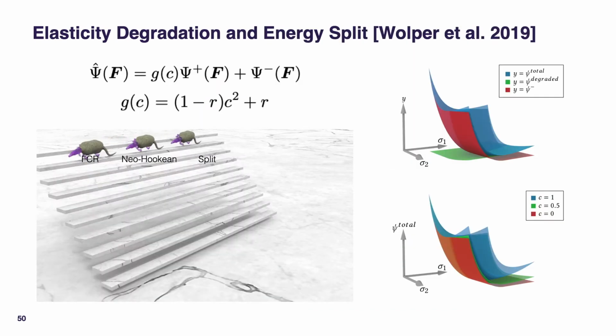But how do we actually design elasticity for fracture? Well, in most works that focus on LEFM, elasticity doesn't need to be heavily modified to allow for fracture because these works hinge on determining whether individual mesh connections have reached some stress threshold, and if they do, we simply break that connectivity. Conversely, in continuum damage mechanics, elasticity and damage are directly coupled through the aforementioned notion of elasticity degradation. So let's go into that a little bit more here.